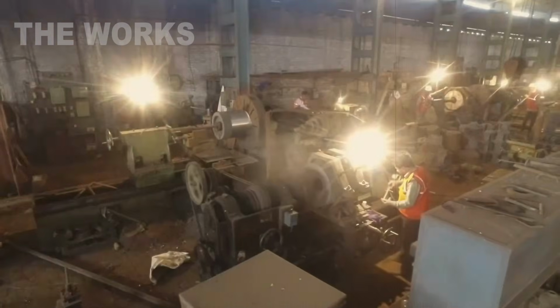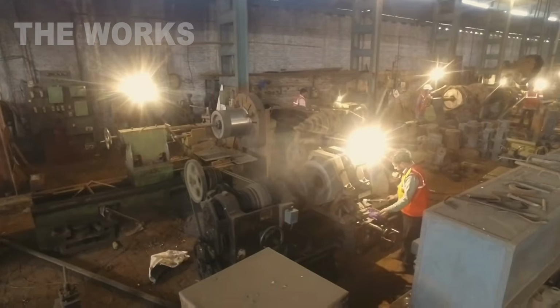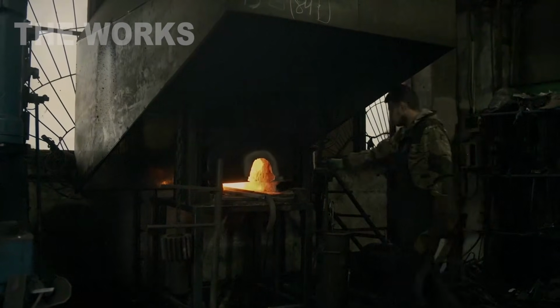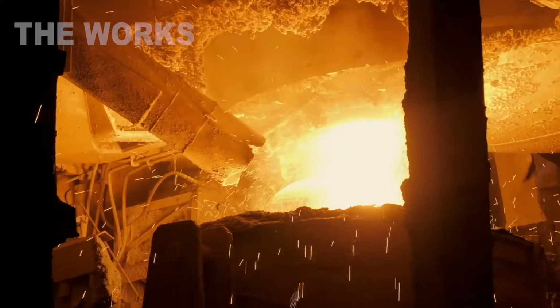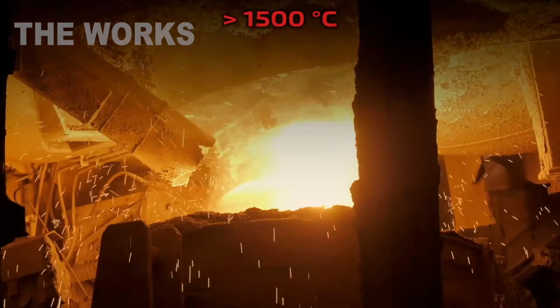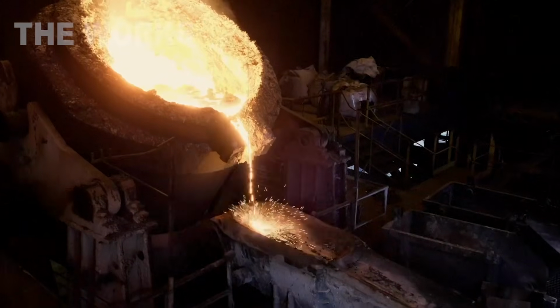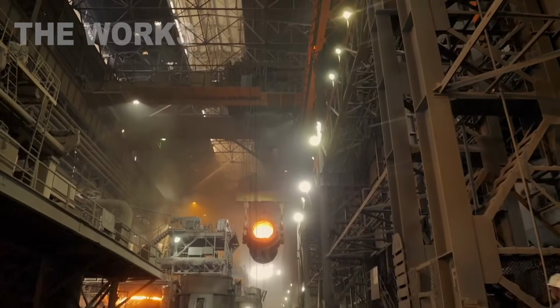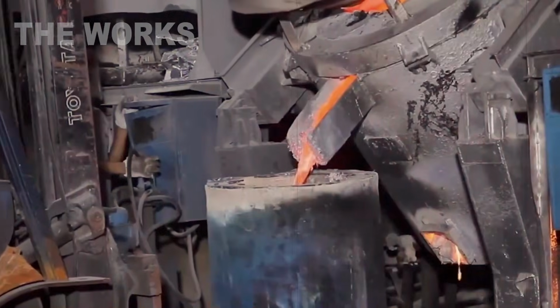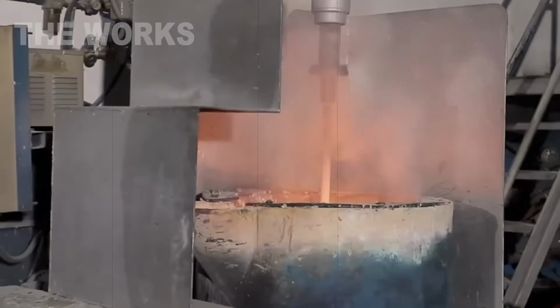Now, the concentrate heads to the smelter. It's dried and then heated in electric furnaces to temperatures exceeding 2,700 degrees Fahrenheit. Air is blown through the molten metal to oxidize iron and sulfur impurities. Sulfur oxidizes to sulfur dioxide and gets removed as exhaust gas. Iron oxide is removed as fayalite slag.